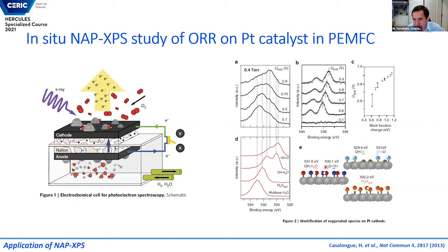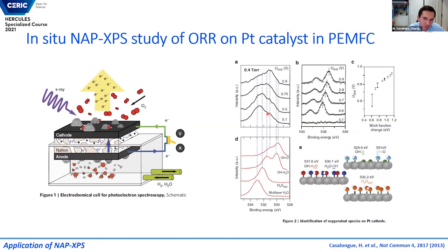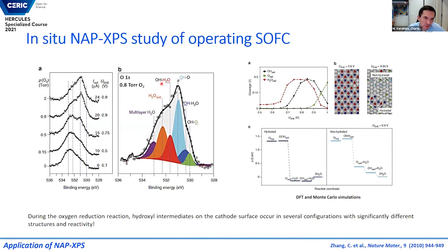And then, having such measurements, you can try to explain what happens on the surface at different potentials: when just pure water adsorbs, when you have dissociation to OH groups, and then the formation of some complexes which are OH with oxygen, and so on. So everything comes from the spectra. You can also fit these spectra more precisely, to try to detect what species you have there.